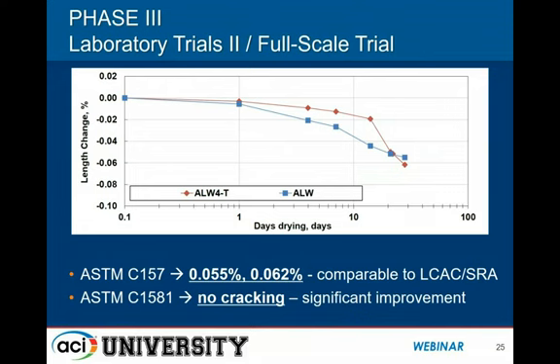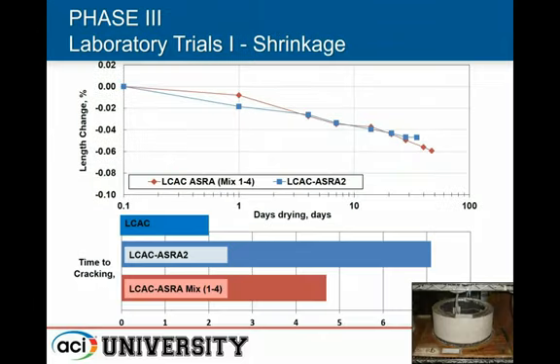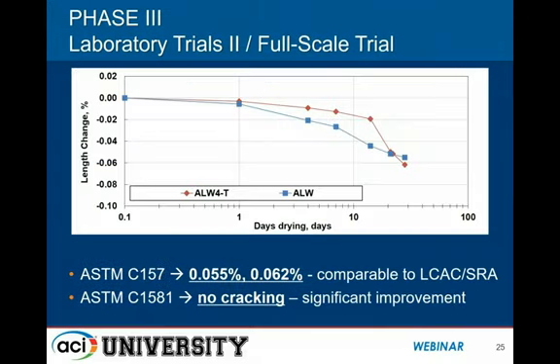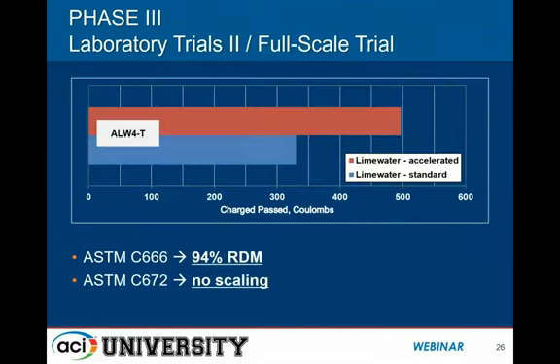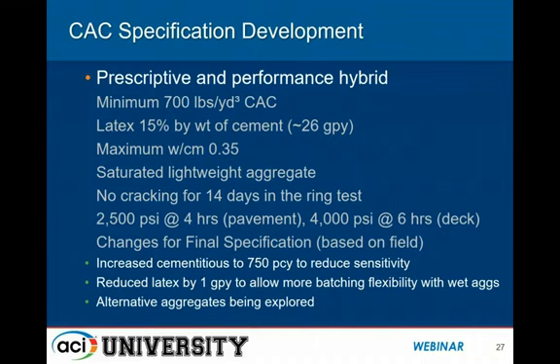They went out past 28 days, which is considered, in the ring test, essentially the gold standard. But remember, just 2 slides ago, I was showing you that these concrete mixtures without the lightweight material were cracking within about a week or so. So with some addition of saturated lightweight aggregate, we've eliminated cracking in the restraint ring. This is a very significant improvement and something that I heavily emphasize as a strategy that works with this material. As I said, it did throw us off a little bit with respect to the early strength, and that's something that you have to design for, but I believe it can be accommodated.